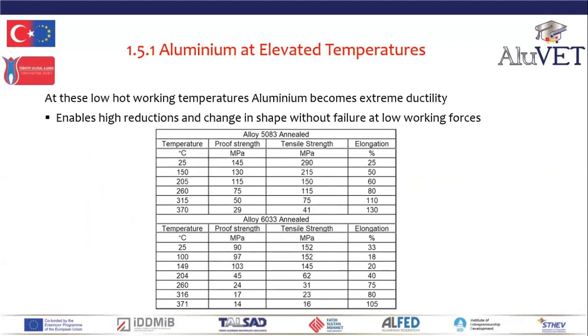Now, at elevated hot working temperatures, the atoms expand. The expansion weakens the metallic bond, so the aluminium becomes extremely ductile, superplastic. This allows large amounts of deformation, reshaping without failure. Thus, hot working enables high reductions, such as extrusion and change in shape, without failure at extremely low working forces.